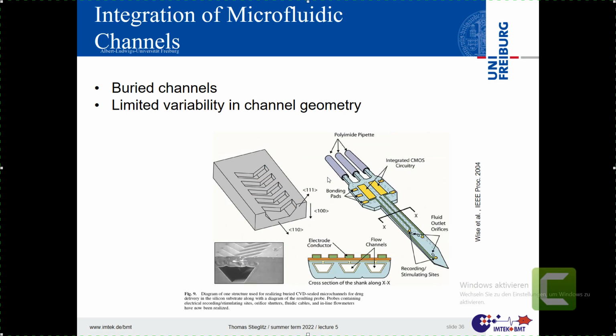And at the end, you throw everything in an etching bath of EDP, and then you get the probes. They were very creative in combining them with also microfluidics. That means you have to make a channel into silicon. First, open a channel, and second, close the lid of the channel, otherwise it's not a channel, you know. And that was really demanding, and they played a lot of tricks here. For example, to have that chevron-like pattern of the surface layer, which allows the entry of etchant solution. Then you etch out that groove.